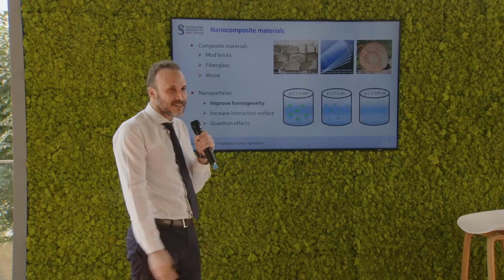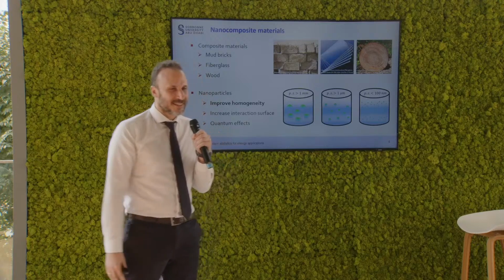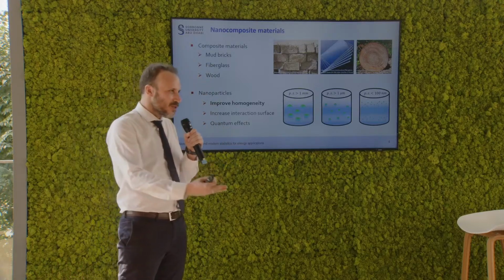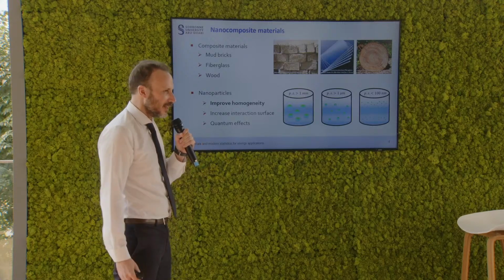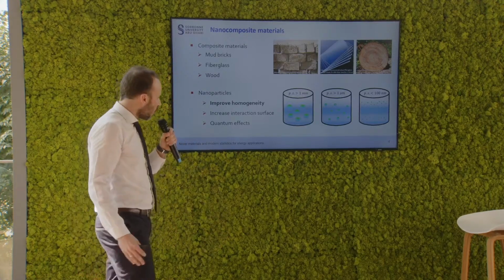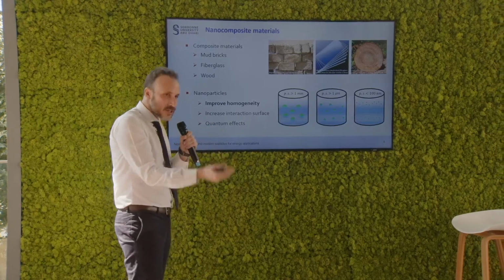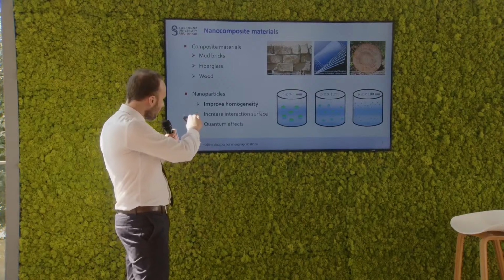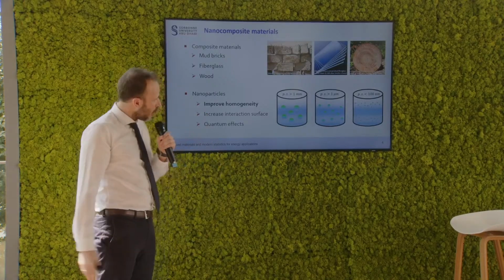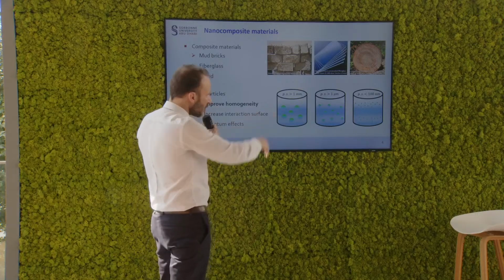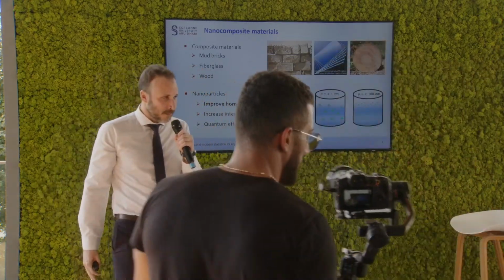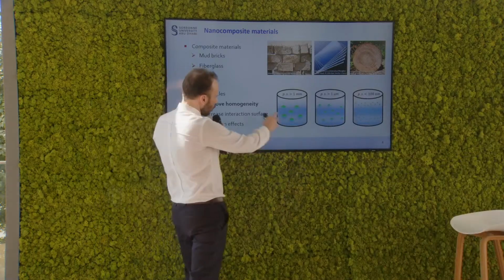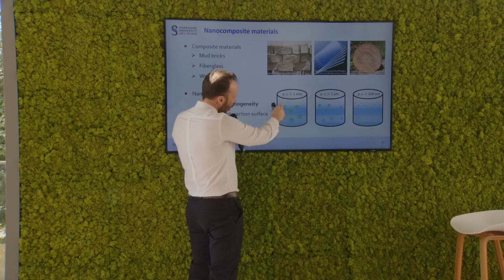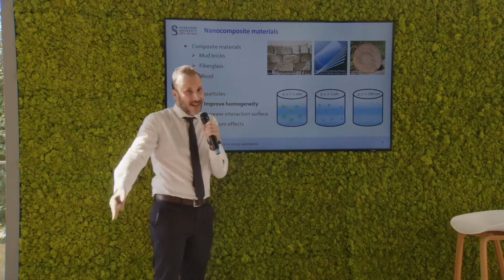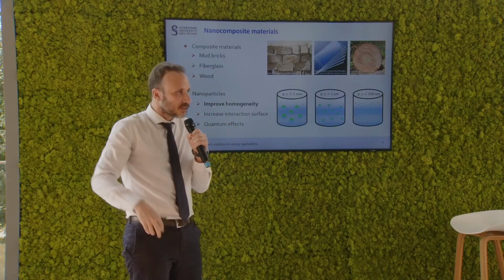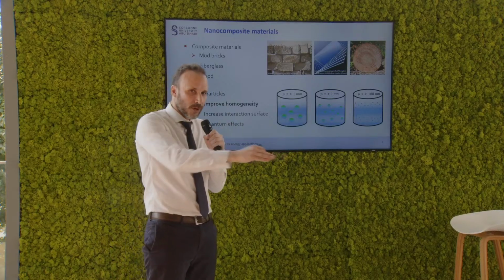Now, generally, scientists have been very much inclined, the last couple of decades at least, to create composite materials that use nanoparticles in them. And there are several reasons for this. I thought I should list at least 3 of them. So as we see over here, nanoparticles, due to the nanoscale of their dimensions, can improve the homogeneity an enormous amount. We have 3 solutions here, each of which has a different size of particles as a solute in them. And as you can see, the one with the bigger particles over here will have regions where the particles cover more or much less of a particular area. That means the properties of the solution vary enormously from one point to the other.